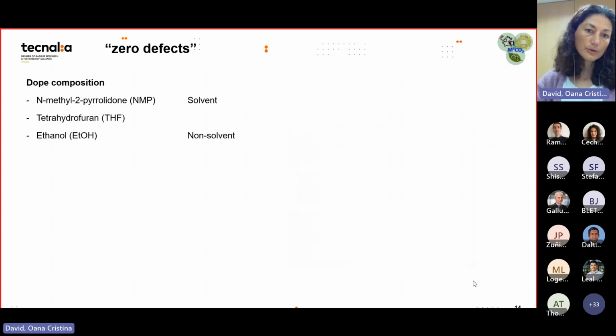Going back to our example, here we had NMP as solvent and ethanol as non-solvent, and we also added some THF to the NMP. This is like a co-solvent up to a certain concentration. If we have only THF, then it behaves as a non-solvent. But the main point of THF is that it's more volatile than NMP, so it can promote the outer skin formation in the air gap when you have evaporation of the solvent.